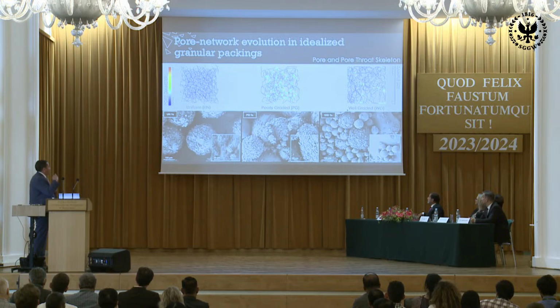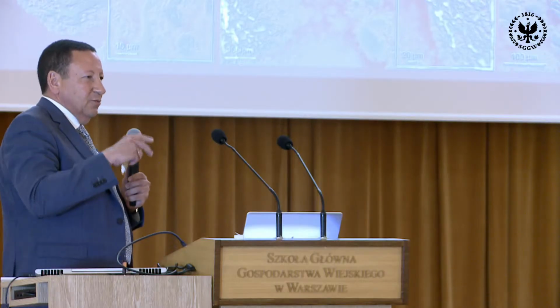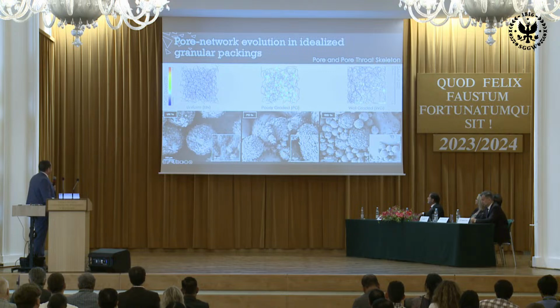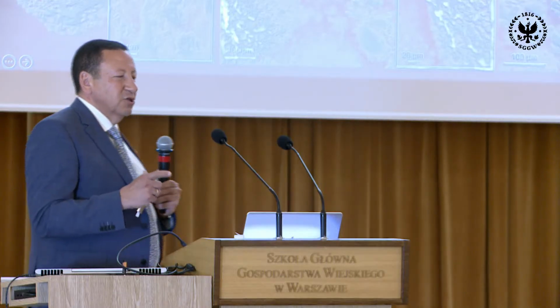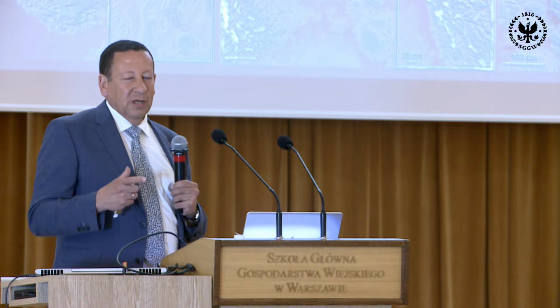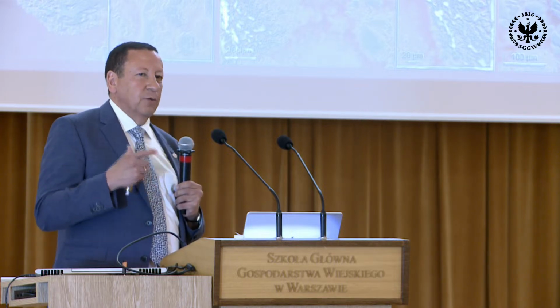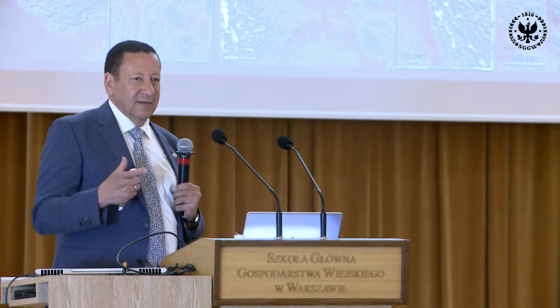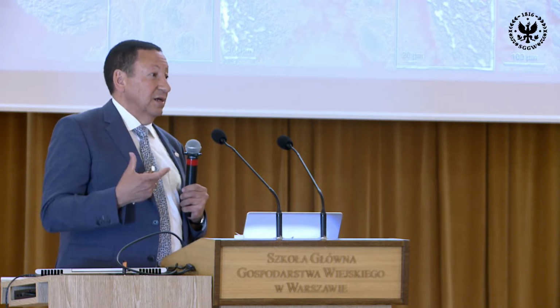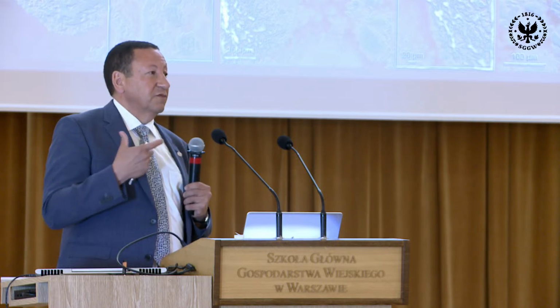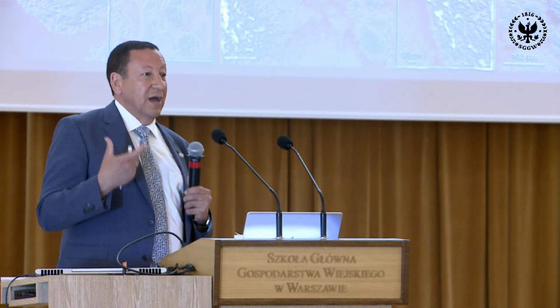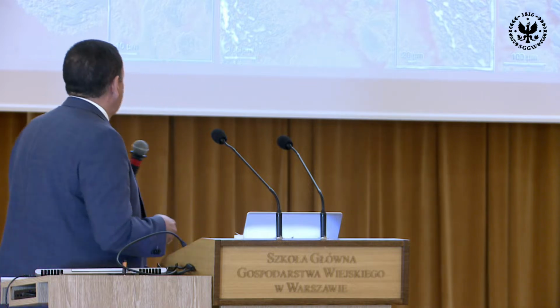Then we upscale a little bit to see how this is happening at different stages. Now we are at 10 micrometer size. What you see here are those precipitates, and as you can see, they are not occupying the entire volume. Basically, they are not changing the hydraulic conductivity significantly. Actually, we change the permeability by 1 order of magnitude, just that. So it means we keep porous materials porous, whereas one of the issues with cement, for instance, is that you impermeabilize the material and create issues with groundwater flow. This is not the case with biocementation.